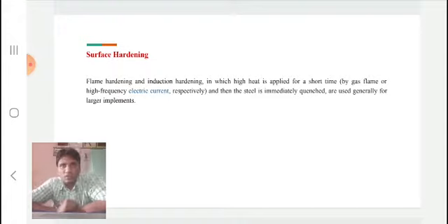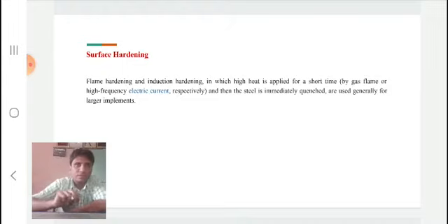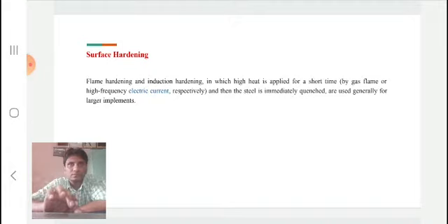Generally, a lower depth of hardness layer is created than for flame hardening, with a short cycle time, making it suitable for smaller parts. Quenching with water, oil, or air should quickly follow using a separate quenching ring integrated with the coil assembly. Several types of inductor shapes exist to match these part shapes.